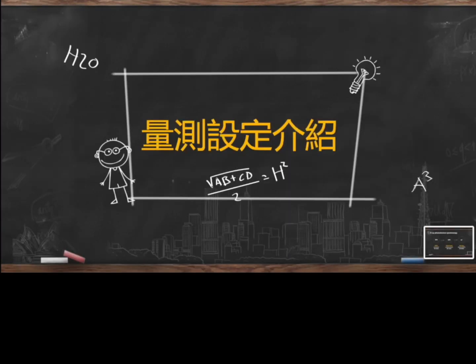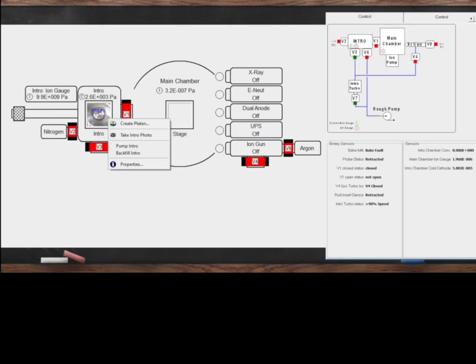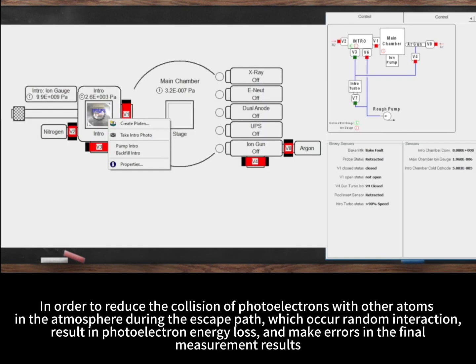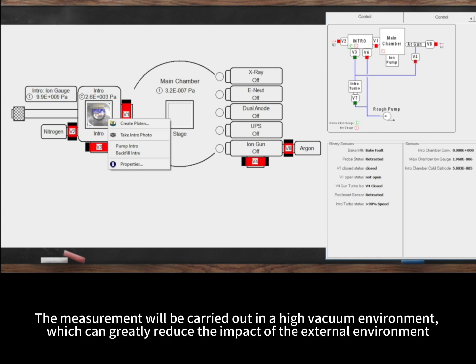Introduction to pre-measurement settings. In order to reduce the collision of photoelectrons with other atoms in the atmosphere during the escape path, which occur as random interactions, result in photoelectron energy loss, and make errors in the final measurement results, the measurement will be carried out in a high vacuum environment, which can greatly reduce the impact of the external environment.